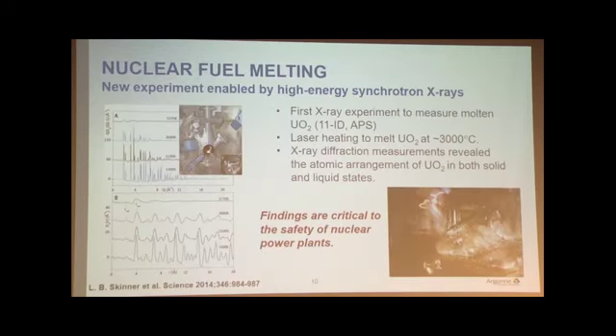Talking about nuclear fuel, it's a very different problem, because in this experiment researchers want to look at the nuclear fuel melting process. In order to do this experiment, you need to heat the fuel to 3,000 degrees C. And you also want to watch how the fuel evolves during this melting process. It's an extremely difficult experiment. But it's made possible, again, this experiment was done at APS. Researchers built this complex sample environment and were able to use high-energy X-ray to do a diffraction experiment. This diffraction experiment tells us the atomic configuration of the uranium and oxygen distribution in both solid and liquid. So this finding is very important to understand the nuclear fuel melting process.